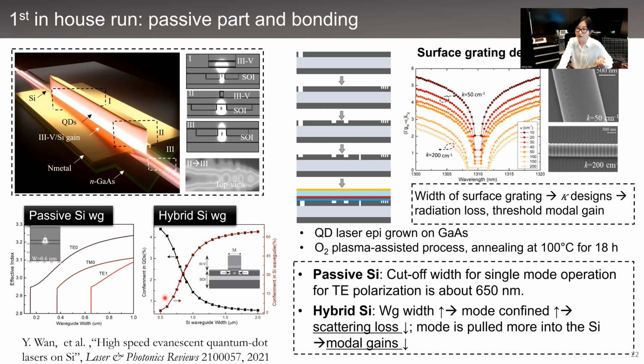And for the hybrid part, the optical mode is laterally confined by the silicon waveguide, while a portion of the mode evanescently overlaps the III-V quantum dot region. So this figure shows the simulated optical mode confinement factor in the quantum dot region and in the silicon waveguide for various silicon waveguide widths. So with the increase of the silicon waveguide width, the guided fundamental mode is more tightly confined and has less interaction with the edge of the silicon waveguide. This leads to lower scattering loss.